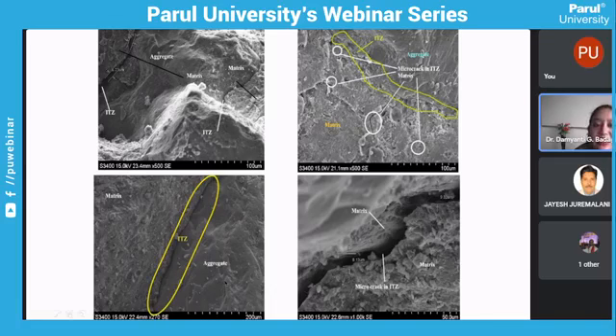Here you can see the aggregate, matrix, interfacial transition zone, and after breaking, the concrete has some internal cracks. That crack is very minor, 6.73 micrometer, 6.41 micrometer. Okay, here you can also see the aggregate microcrack in the interfacial transition zone. That was not measurable, so I didn't mention the measurement here, right? But in another image, you can see the microcrack in the interfacial transition zone, and that was 8.13 micrometer.